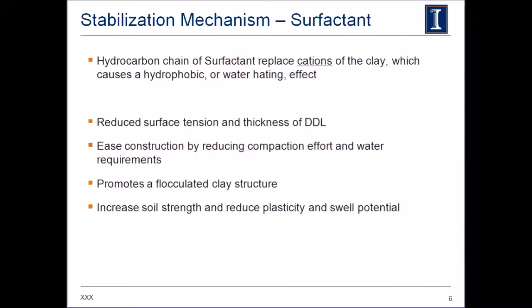If cationic surfactant is used, its cation would be attracted to the clay surface by cation exchange, which promotes a flocculated clay structure. The effect of this is increased strength, reduced plasticity, and reduced swell potential.